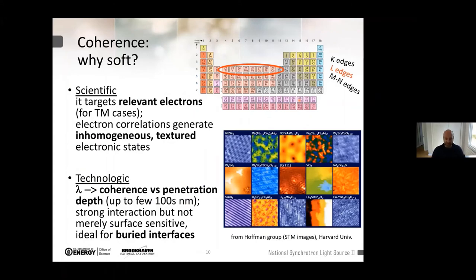Indeed, so why coherence and why soft? Why soft? Let's recap. In terms of scientific motivation, there is a relevance in the target electrons that we are aiming at. L edges for transition metals are the way in which you would like to tune to electrons that are actually bringing the information out of the electronic order, correlation and so on and so forth, that develops in relevant cases. And the other is that luckily, for the same reason, if you take most of the cases of interesting available materials in nature, here we depict some cases taken from one of the groups at Harvard University through STM images, you will see that there is any kind of rearrangement, inhomogeneities, and so propagation vectors potentially, if the structures are regular, that are present, and so we have a plethora of cases that are worth and very interesting to be studied indeed. Right? And so inhomogeneities and textures in particular are relevant per se. And again, the coherence will play a major role.